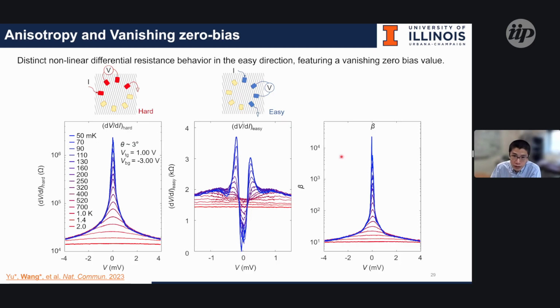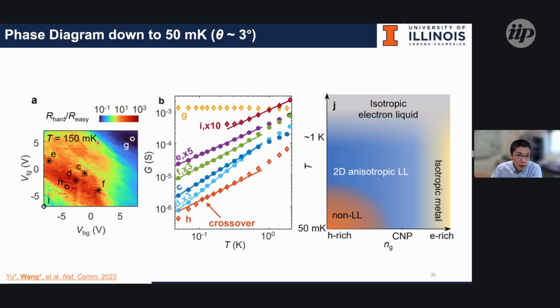And also, as you can see, the anisotropy in the system. If you further explore the system, you can see it can be categorized by a few different regions, which we call a phase diagram. Near the charge neutrality, up to a very high temperature, you can see the highly anisotropic Luttinger liquid behavior, but as long as you dope the system to very high electron doping,